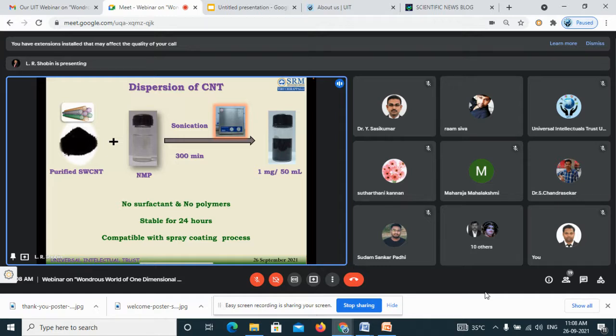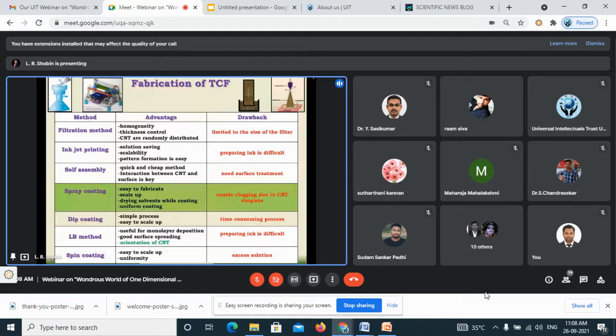And interestingly, this suspension you can spray on any substrate. So if we have a solution, you can make a film through different processes. You can couple any two of these processes and get decent films. You can use the filtration method, or you can spray it. You can dip coat it. You can use spin coating. So many processes you can use. However, each method has its own advantage as well as disadvantage. But I'm sticking with the spray coating process because it's relatively easy compared to the other processes.